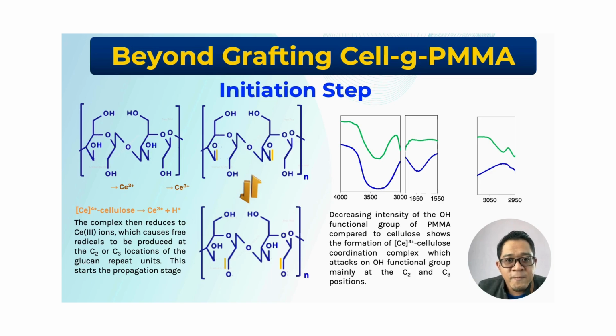And then we can see the decreasing intensity of the OH functional group in the FTIR of PMMA compared to the cellulose, which shows the formation of the Ce4+ cellulose coordination complex with attack on the OH functional group mainly at the C2 and C3 position. The formation of an aldehyde functional group, HC double bond O, occurs during the breaking of the bond at the C2 to C3 position.